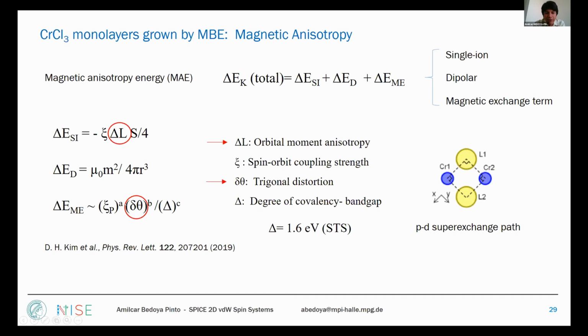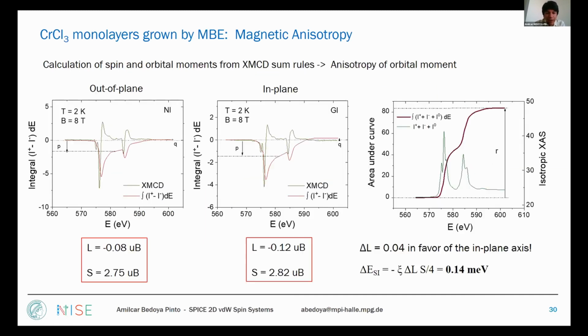So for our system, this degree of covalency, which is also the bandgap we extract from STS measurements, and the spin-orbit coupling strength can be taken from literature values for chromium and chlorine. And what is important for us is to determine why our anisotropy is so high, and whether there could be any orbital moment or trigonal distortion in our MBE-grown samples that will explain this large anisotropy in the plane.